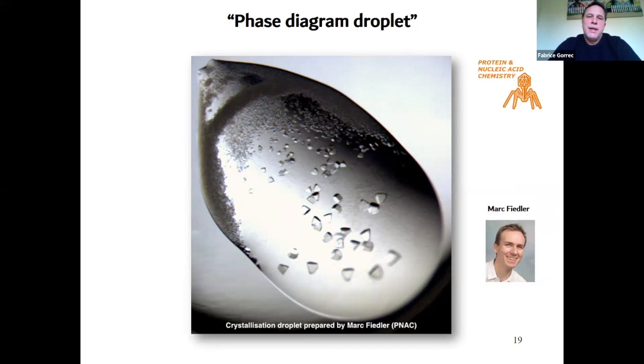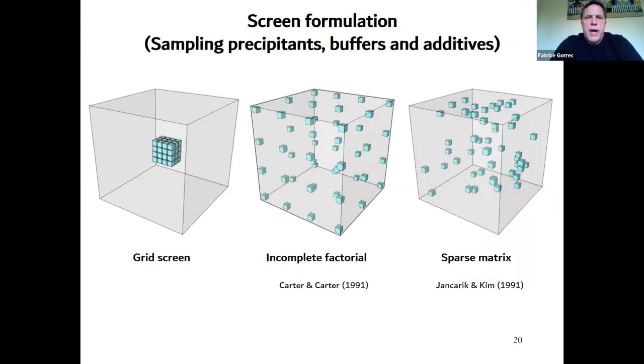You could also have a doubt about something, that there's probably liquid-liquid diffusion before vapor diffusion. And that would be because at this scale, with the small droplets, we don't really mix the condition, the precipitant, with the protein sample. So at the beginning, you could suspect that there's liquid-liquid diffusion at the same time as vapor diffusion. So in a condition, there's not only precipitant. Usually we have three main categories, which is precipitant, buffers, and additives. And to sample all those, the plethora of suitable reagents, we design screens.